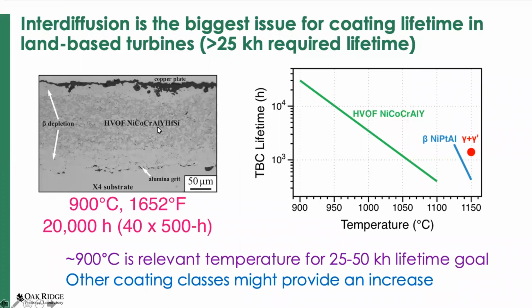But in fact, you can look at this specimen that's been exposed for 20,000 hours at 900 degrees C and see that we've already degraded sort of half the coating. The darker region is the beta, aluminum-rich beta phase. And we've got depletion here. And because of interdiffusion, we've got depletion here. The alumina grit is marking that original interface between the coating and the superalloy substrate.